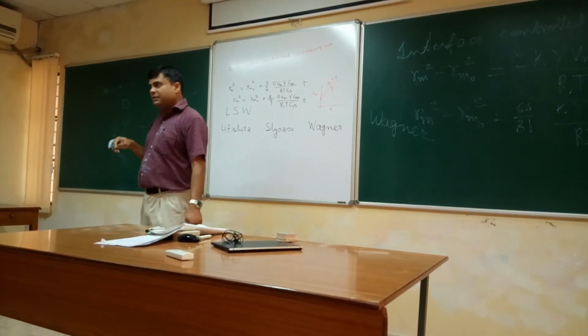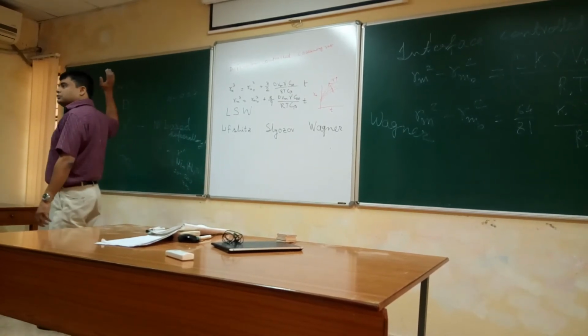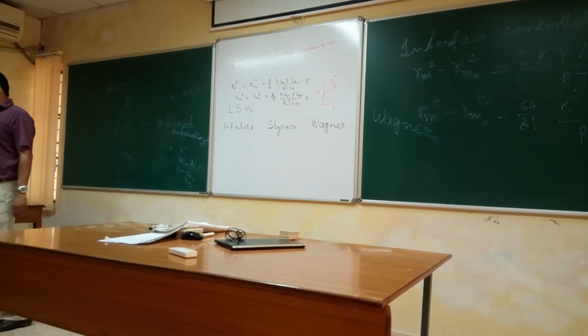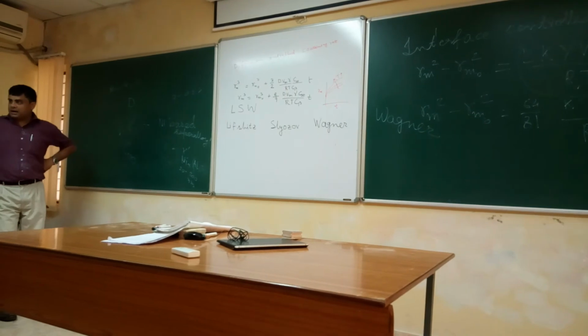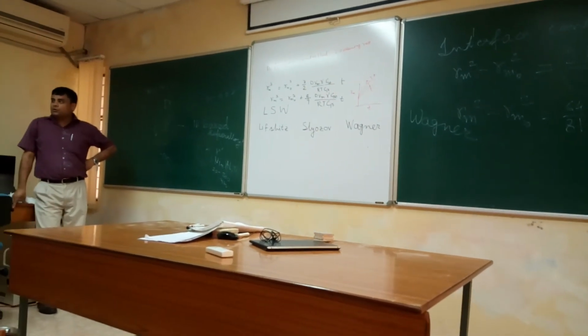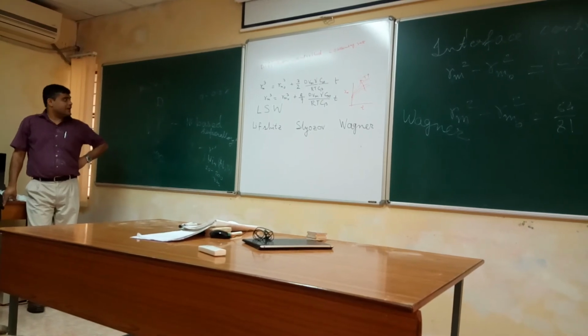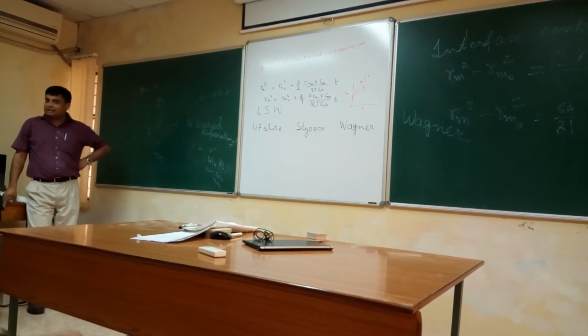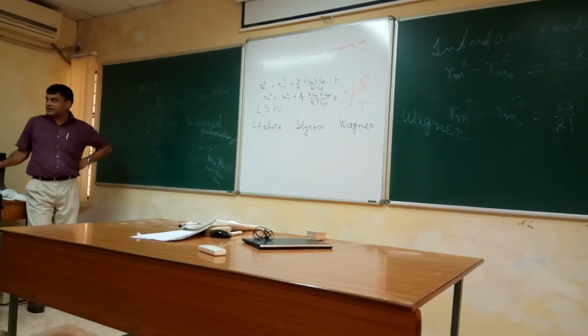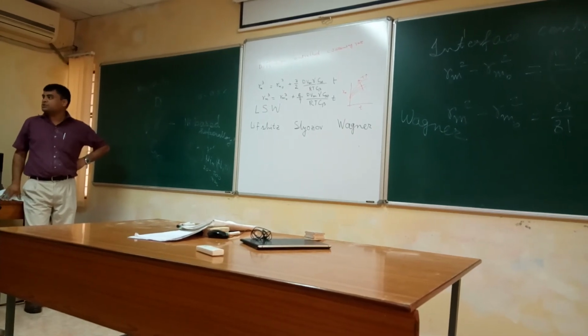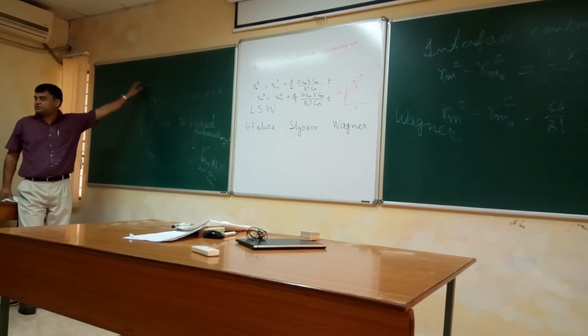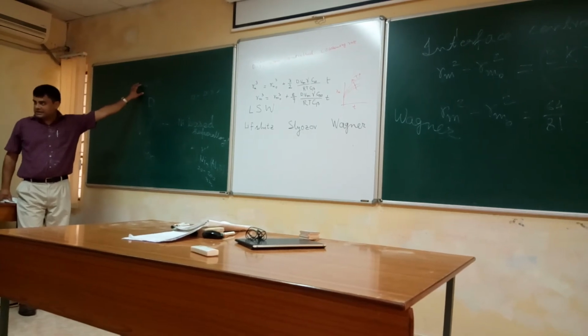So by lowering diffusivity, those carbides, moly carbide or chromium carbides, do not coarsen. So you also get secondary hardening, and those carbide precipitates do not coarsen because of the lower diffusivity of the substitutional elements in that case.